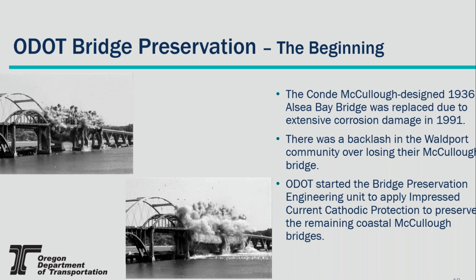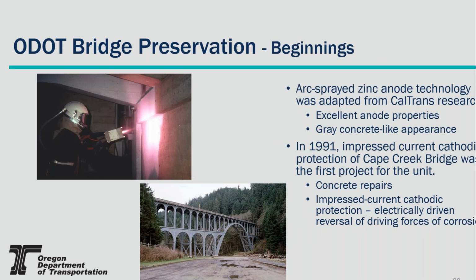So one of the key elements of that technology was the arc sprayed zinc. There was some research done in California by Caltrans with arc sprayed zinc, and what we found there was a metal with excellent anode properties that is gray, and so you put it on your concrete, it doesn't look that out of place. And so in 1991, at the same time as we were demolishing the old Alsea Bay Bridge, we put cathodic protection on the Cape Creek Bridge. That was after concrete repairs were done, and you see the results on the lower center picture. The upper left picture is the arc spray application, and Dave will cover that more. And I believe we're at the point of switching control.